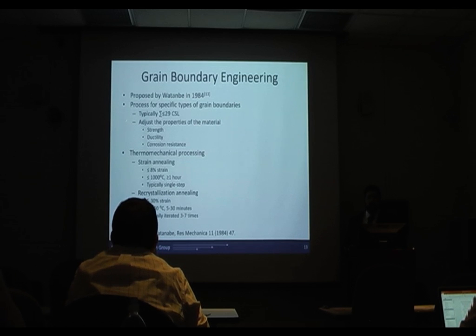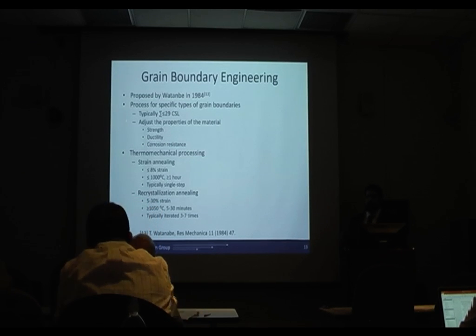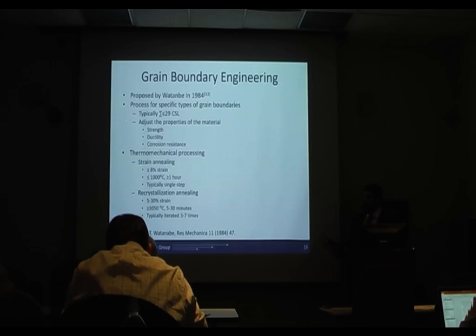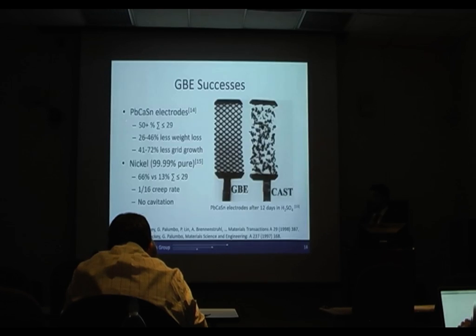And that's generally broken into two subsets for grain boundary engineering. You have strain annealing, where you put in a relatively small amount of strain and heat it at a low temperature for a long period of time. This is typically a single-step process, but there are multi-step processes that exist. And then there's also recrystallization annealing, where you put in more strain, 5 to 30%, heat it at a higher temperature for a much shorter period of time, and then iterate this, generally 3 to 7 times. So this has been shown to be successfully applied in service conditions.